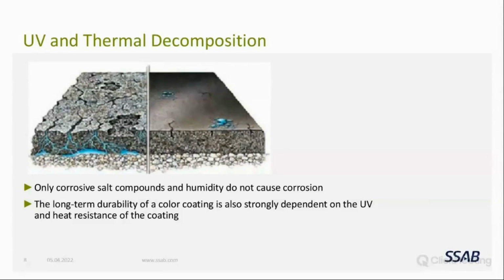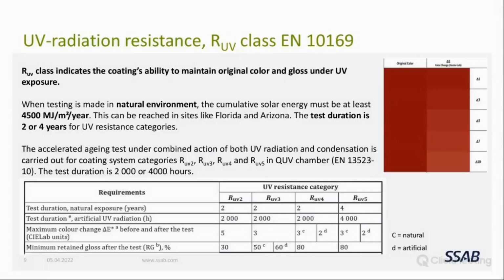Not only corrosive salt compounds and humidity cause corrosion, so the long-term durability of a color coating is also strongly dependent on the UV and heat resistance of the coating. On this slide is told how RUV class indicates the coating's ability to maintain original color and gloss under UV exposure. These RUV categories are also based on this mentioned standard EN 10169, and when testing is made in natural environment, the cumulative solar energy must be at least 4,500 megajoules per square meter per year.